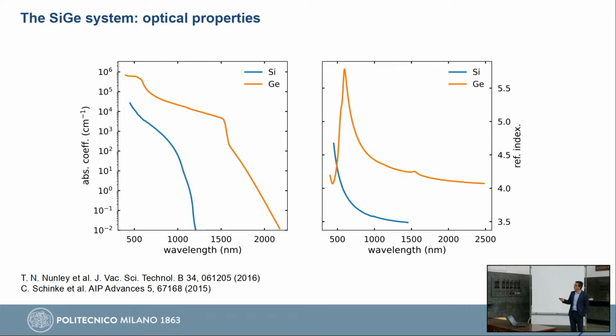If we look at the optical properties, so the absorption coefficient, I've already discussed this a few minutes ago. So basically, the takeaway message is that germanium is a strong infrared absorber, silicon is transparent in the infrared. And if we look at the real part of the refractive index, we see that germanium has a much larger refractive index than silicon. So for example, in a waveguide, where I need some refractive index contrast to guide light, I can play around with these two materials to have a waveguide made of silicon and germanium.